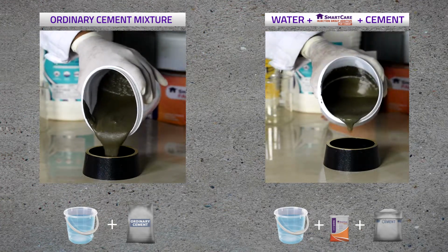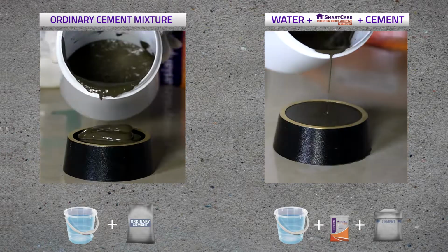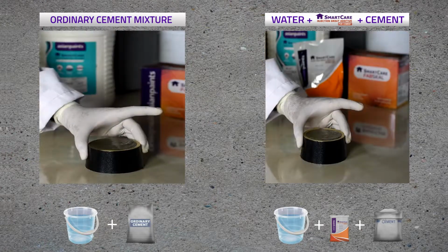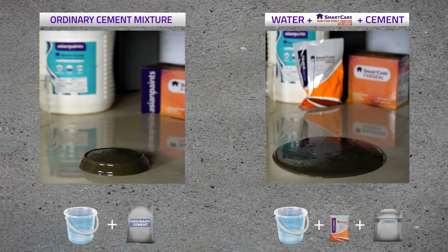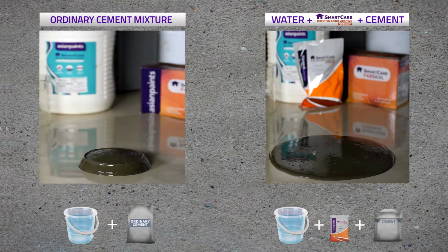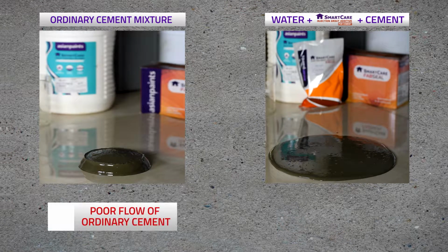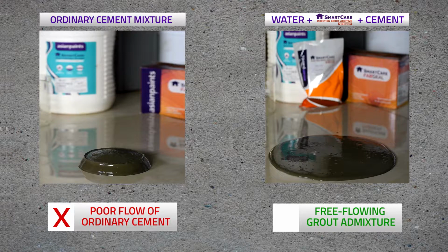These mixtures are then added to a flow cup. Once the cup is filled to the brim, it is lifted to check material flow. We observe that cement is really stiff and does not flow much, whereas cement with SmartCare Injection Grout Additive has a very good flow. The stiffness of ordinary cement indicates poor flow, which would make deep penetration of narrow cracks very difficult. However, the low viscosity cement slurry produced using SmartCare injection grout additive can be easily injected in narrow crevices to effectively fill voids.